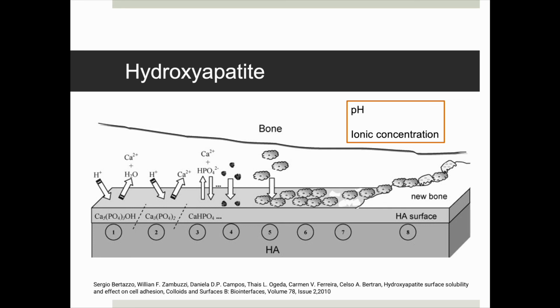Calcium ions in the HA lattice are held in place by trivalent phosphate ions. A fall in the solution pH can cause a change in the protonation state of some trivalent phosphate ions, converting them to divalent phosphate ions. This conversion weakens the calcium phosphate bonding and thus allows some calcium to be released into the solution. Divalent phosphate released into the solution binds with hydrogen ions to form monovalent phosphate ions. This binding of phosphate with hydrogen ions in the solution acts as a buffer, altering the pH of the solution and slowing down the HA degradation.